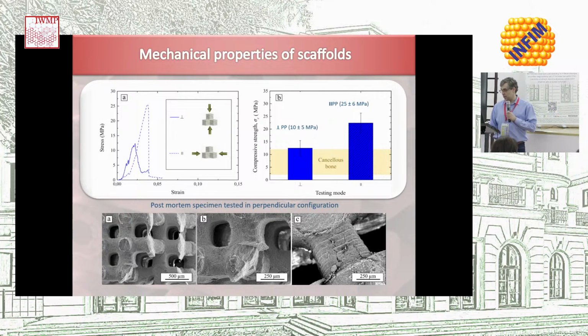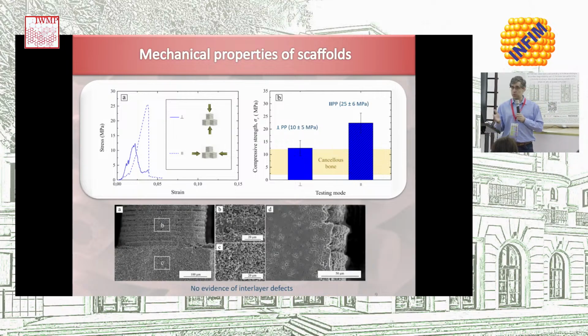And the reason for that is that we observe these hourglass-shaped cracks, which are typical of laminate materials. And this means that the cracking is occurring by a shear process, and this means that there must be some defects in between each of the layers that you have deposited during the printing process. Although we are unable to see those defects, they must be there, okay? You can see the steps on the surface, but there is no actual line of defects aligned with each of the interfaces. So bonding seems to be good, but still there must be some defects producing this shear cracking, okay?